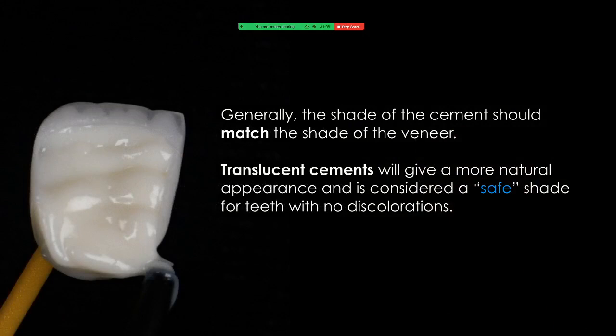Important points to remember. For ceramic crowns, use dual cured resin cements, and the crown should be cemented using light gradual pressure. When loading the cements, margins should be well coated with cements. An oxygen barrier, I use it, and I prefer to use it on the margin.